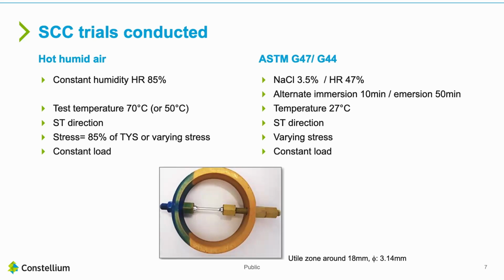The other trial is with chloride, so 3.5% chloride. It consists of alternating immersion during 10 minutes and emersion during 50 minutes, and then we go back to immersion. The temperature is close to room temperature, and the way we load the sample is similar to the other test.